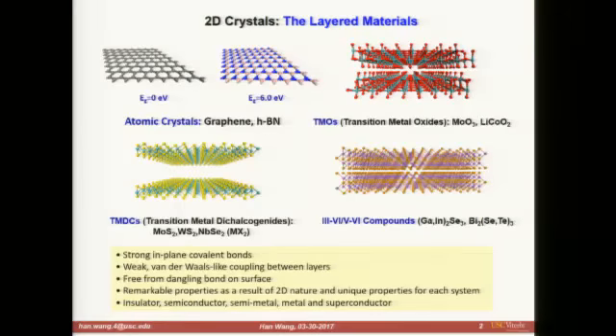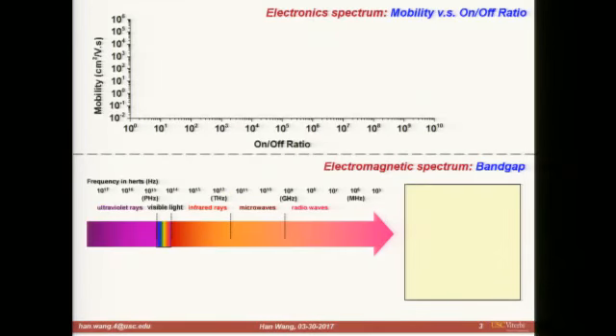Nature has given us a large family of two-dimensional crystals, from graphene to boron nitride to the transition metal dichalcogenides family and other compounds, which all have this layered two-dimensional structure with strong covalent bonds in plane, but only very weak van der Waals coupling between the layers, giving rise to this kind of almost ideally self-passivated material structure that's very attractive for developing new types of applications in electronics, in photonics, and also in their interaction with biological systems.